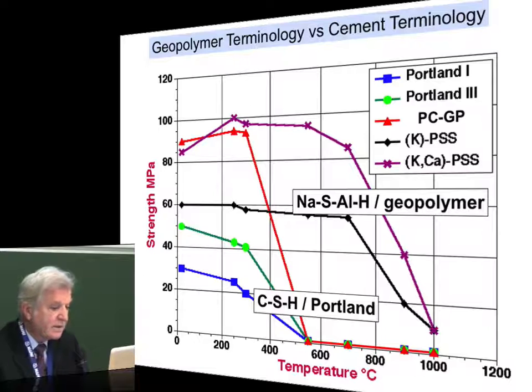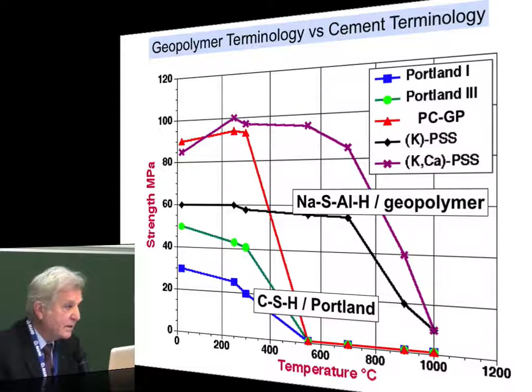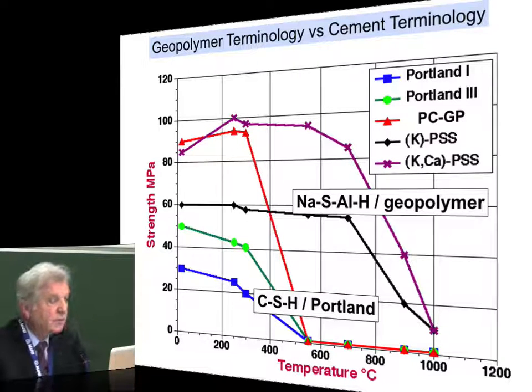And if we compare the behavior of Portland cement materials with the geopolymers, we see that everything that is CSH has no property above 300 degrees C, explodes. Anything that is geopolymer withstands the temperature. So it is very important to use the right terminology, and it is very important to learn the terminology. But cement specialists, or those who want to cope with geopolymer, are reluctant to go back to school.